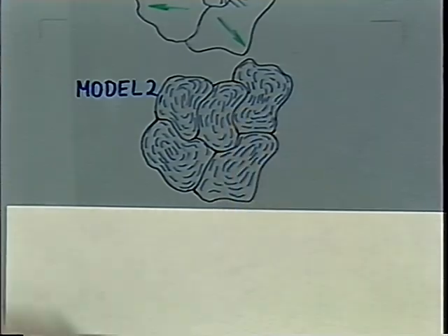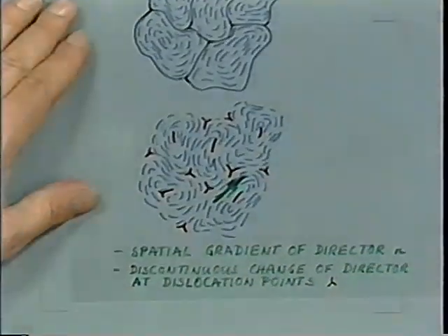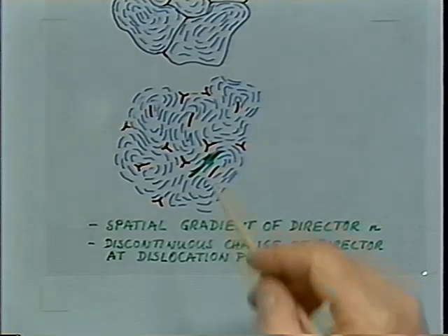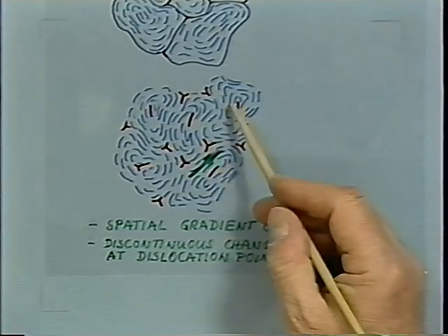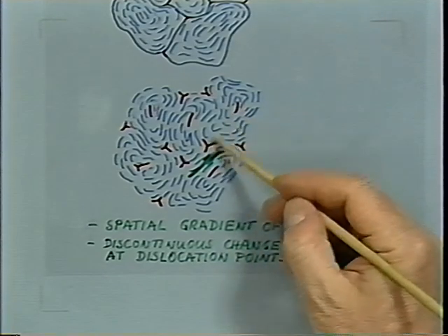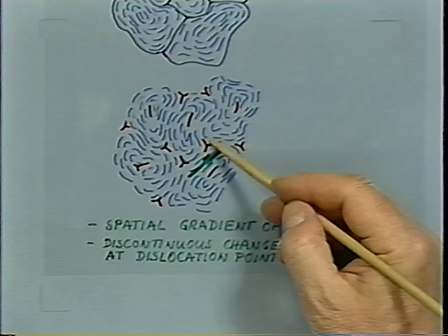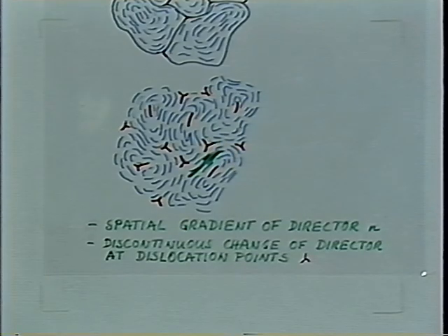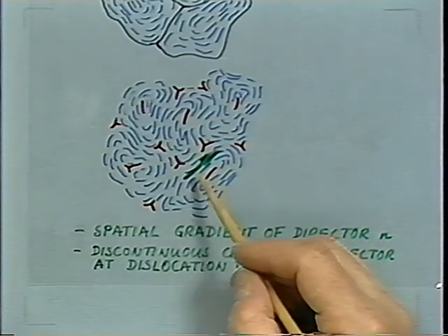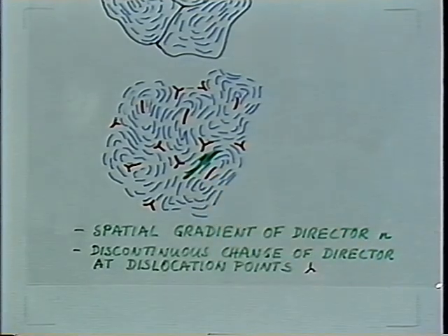Those boundaries actually don't exist, and we can describe this type of domain structure by a set of defects distributed in space. The characteristic length of the texture would be the distance between those disclinations. Locally, we would define a director vector as before. We would have also an order parameter around this director vector.